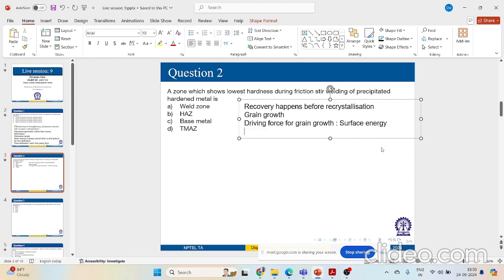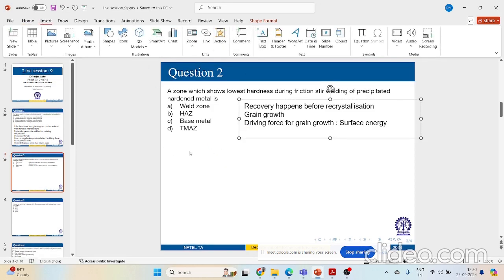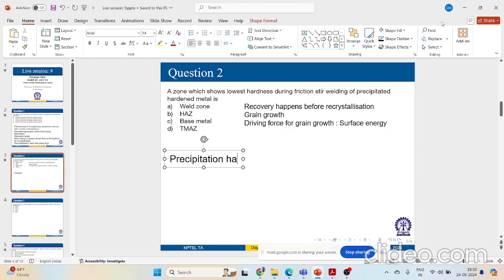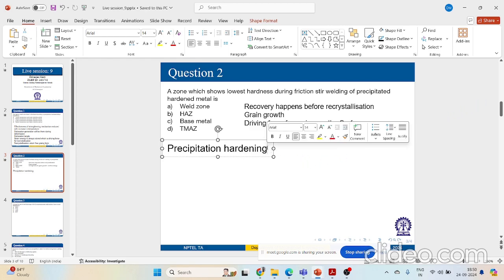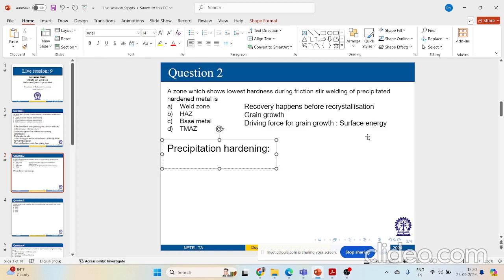So what we will do next, we'll talk about precipitation hardening. If you are thinking of precipitation hardened metals, aluminum alloys are the most frequently welded metals which can be strengthened by precipitation hardening, right? In general, high strength aluminum alloys are more susceptible to hot cracking, then loss of strength or ductility in your heat affected zone.